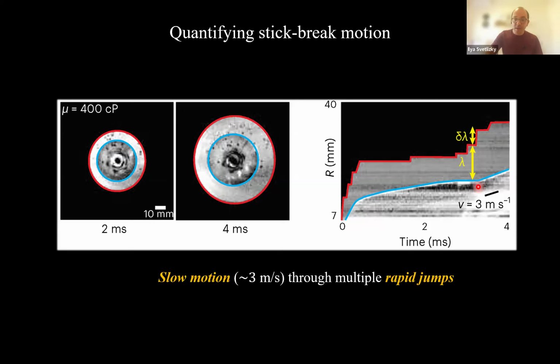And what you see is that the slow motion, so the average motion of the crack, is pretty much the same as the average motion of the fluid. It's really slow, about 3 meters per second. But unlike the fluid, which expands continuously, the crack jumps very rapidly with very long times where there is no motion at all. And along the talk, I will use lambda to denote the lag size. This is the lag where the fluid lags behind the crack front, and the jump amplitude of the crack, which is delta lambda.